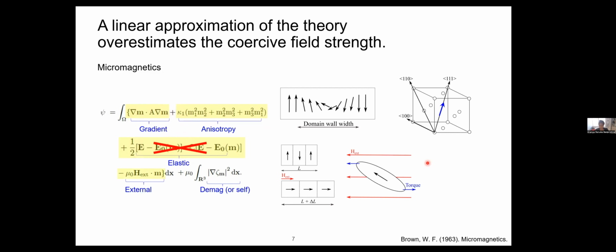And then you have other energy terms. This is, for example, your external field. When you have a magnet placed in an external field, and the magnetization does not align with your applied field, the material experiences a torque so as to rotate the magnetization and align itself with the applied field. And you also have an energy term called the demagnetization energy, which is essentially like a self field. If you have a magnetized body, you have the poles of the magnetic body, that's the magnetization at two end corners, and this generates an external field which affects the microstructures that form in the material.